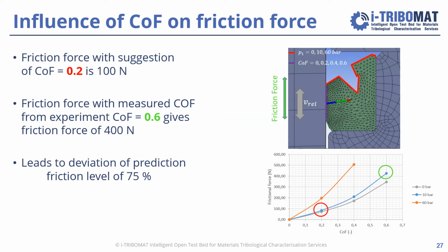Next, looking at the influence of coefficient of friction between polymer and steel shaft on the friction force measured on the shaft in the system. So, for instance, if we use a suggested coefficient of friction value of 0.2, which you frequently find if you have no experimental values, then for our system, for a 10 bar chamber pressure, we get 100 Newton as a friction force measured at the shaft. But if we use the experimentally determined value of 0.6, we get actually 400 Newtons.